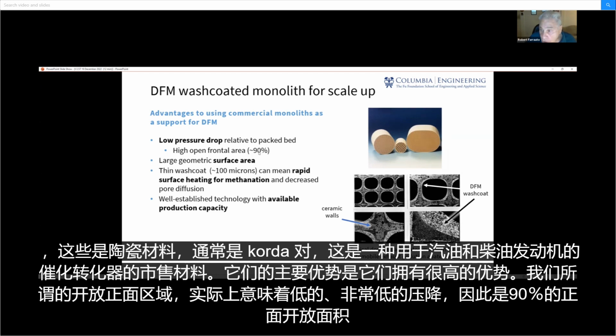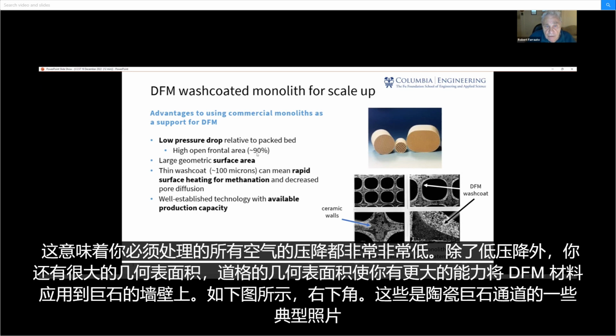very low pressure drop. And therefore, 90% open frontal area translates to very, very low pressure drop for all of that air that you must process. In addition to the low pressure drop, you also have a large geometric surface area, and that large geometric surface area gives you much more capacity to apply your DFM material to the walls of the monolith, and that's shown here in the bottom right.